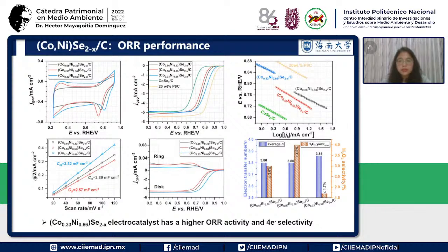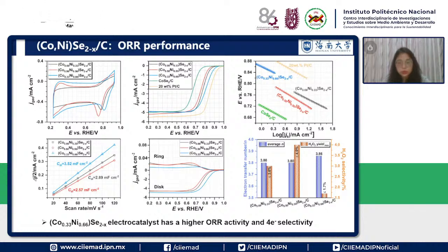Okay, and after the physical and chemical characterization, we tested the ORR activity and the stability. Here we did the CV and LSV and also calculated the Tafel slope. Here we find that in the alkali, these three materials show ORR activity much better than cobalt selenide alone. That means when cobalt nickel selenide forms composites, the activity is much improved. And when the ratio is 1:2, it shows the best ORR activity among these three samples.